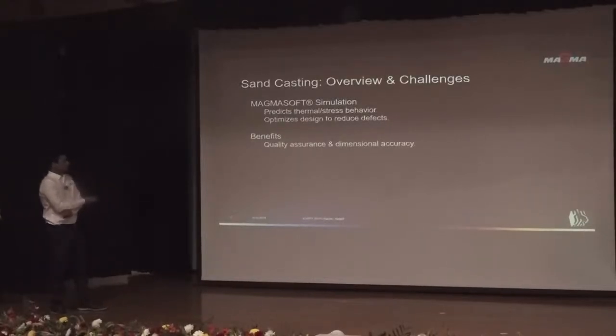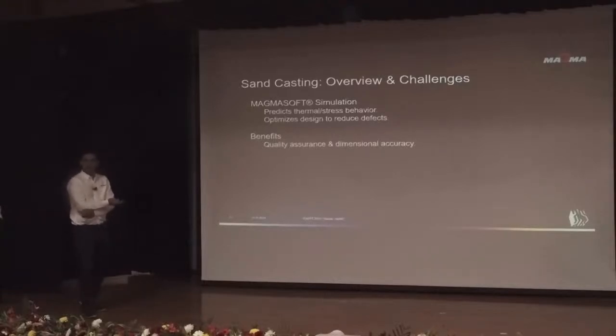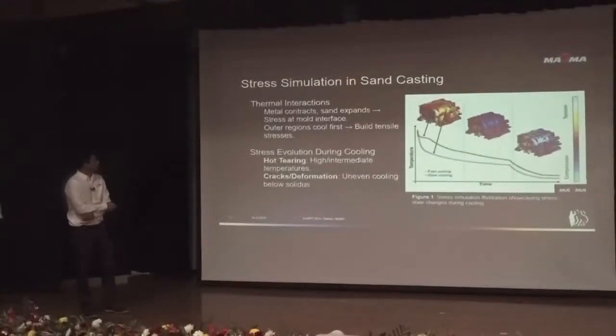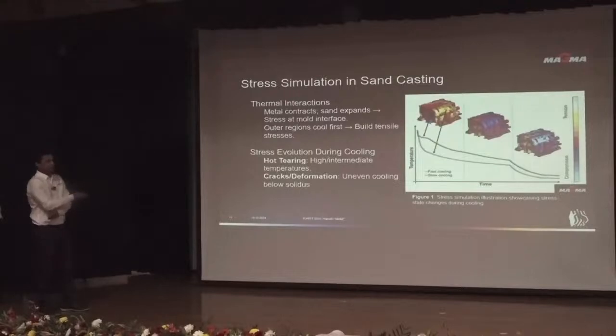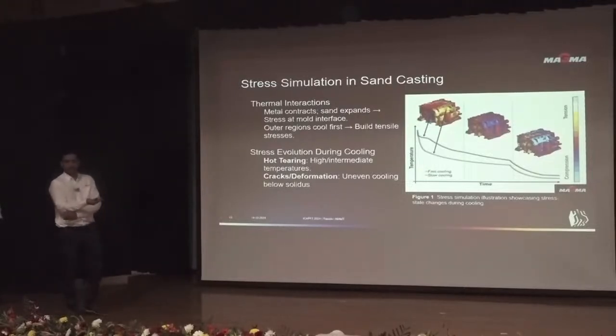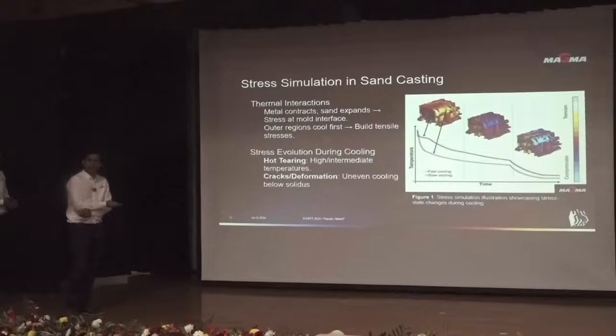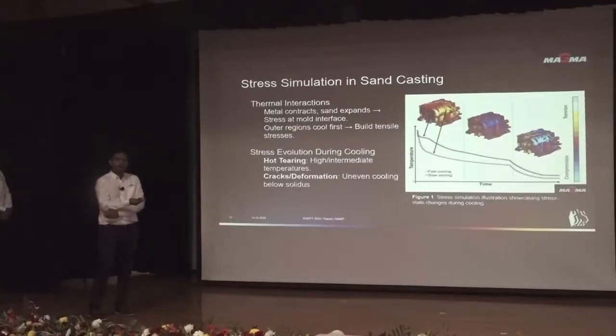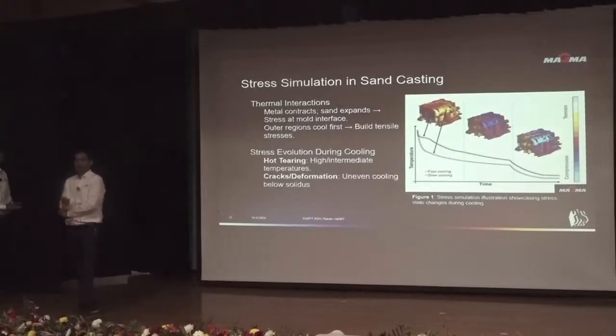So, what are the benefits? Obviously, quality assurance and also dimensional accuracy, if we talk about stresses, because there are contractions. So, what do we get from stress simulations? First thing is that in thermal interaction the metal contracts. Sometimes we have expanding sands, like green sands expand much. And outer regions get cool first, so that's why tensile stresses build up in castings. And later, in the stress evolution during cooling, at high intermediate temperatures the hot tears appear. And after solidus temperature, there is a chance of cold cracks.